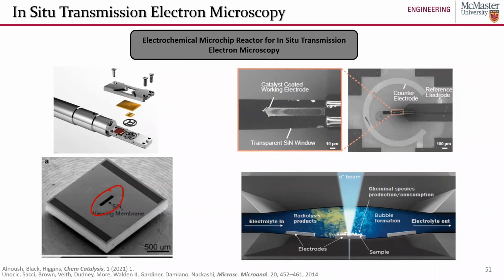If we zoom into what these microchip reactors look like, it's really just a conventional 3-electrode configuration. We've got our working electrode here in the middle with our active materials deposited on it. We've got a platinum counter electrode that surrounds our working electrode, so it's this C-shaped electrode. And then we have our small reference electrode, which in this case is just a platinum metal quasi reference electrode. So why is it called quasi? The terms quasi or pseudo reference electrode are sometimes used interchangeably, and quasi means approximately in Latin. These reference electrodes are not well-defined like silver chloride is, but they essentially serve the same purpose. So that's why it's called a quasi reference electrode.